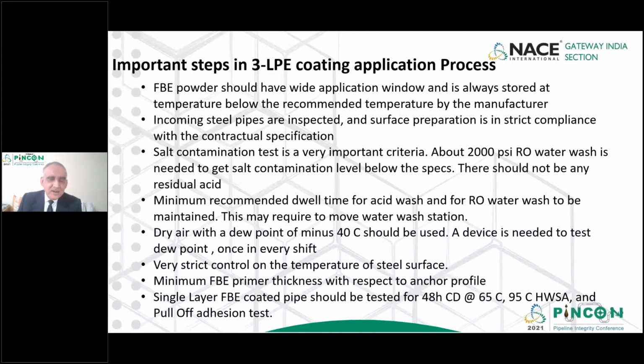Another important recommendation is that the steel temperature should also be kept high at the time of application, because higher steel temperature will ensure a good wetting of the molten powder, and it will always give a high performance. So that is why there are companies who have now specified that a minimum of 230 degrees Celsius is needed. FBE should not be applied for temperature below this requirement.